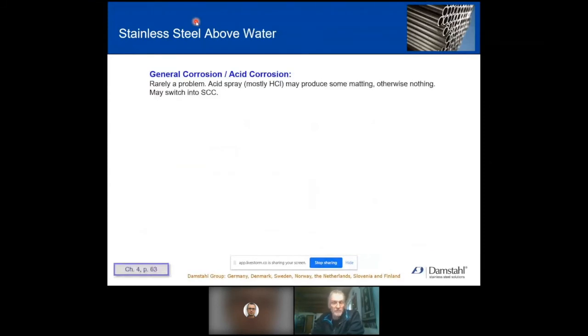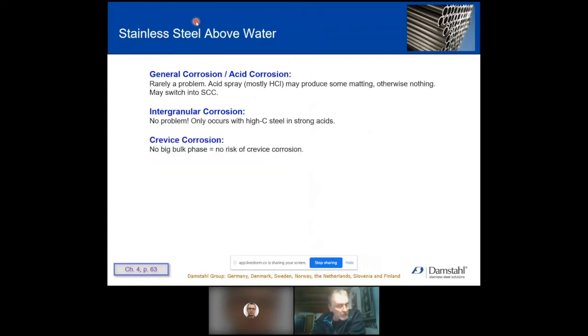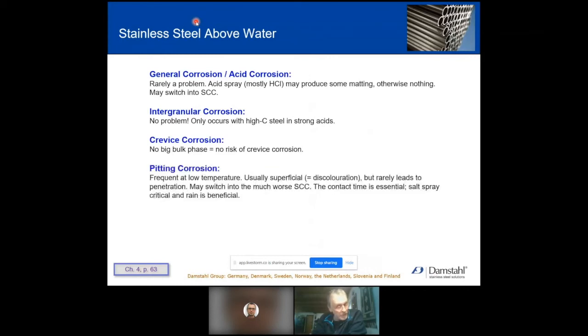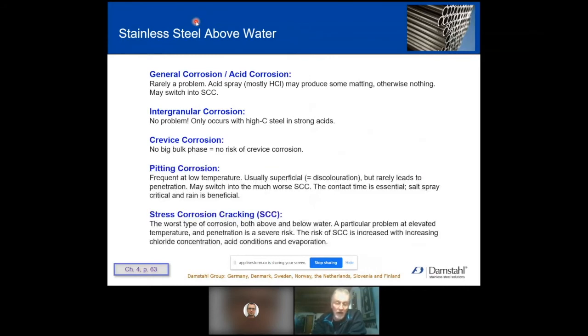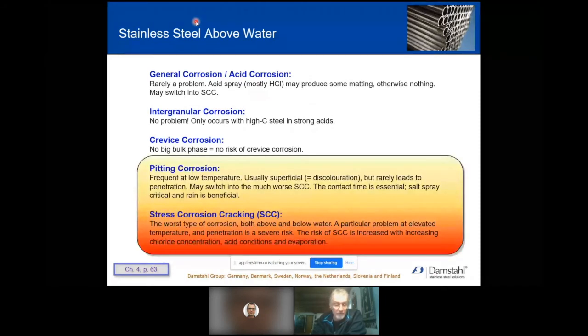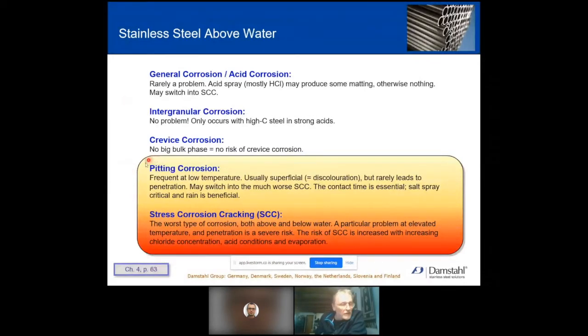Usually the risks we have to take into account above water, as before, general corrosion, that's a sulfuric acid problem. Forget about that one. Intergranular corrosion, forget about that one. You buy low carbon steel and you'll never see that one. Crevice corrosion, we don't have any bulk phase, which means we don't have any crevice corrosion. Pitting corrosion and stress corrosion cracking are quite reasonable risks, especially at slightly lower temperatures, high chloride. Usually pitting corrosion is the biggest one.